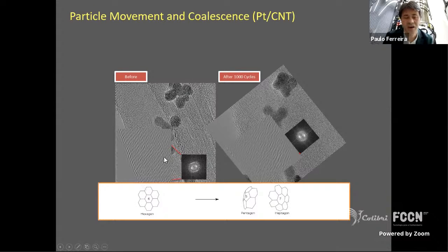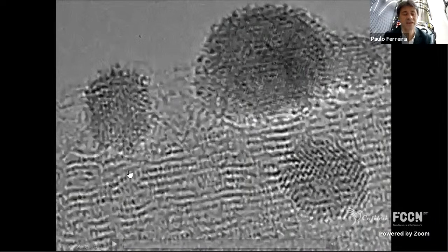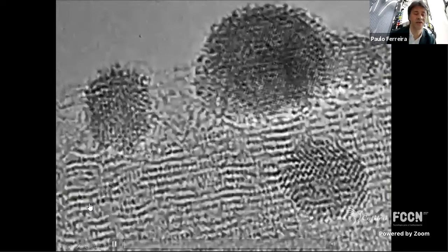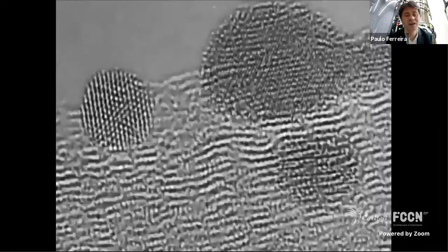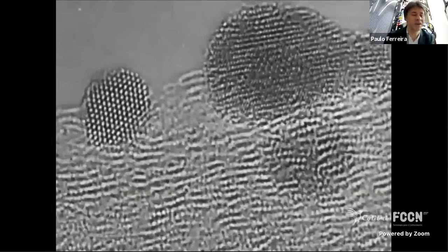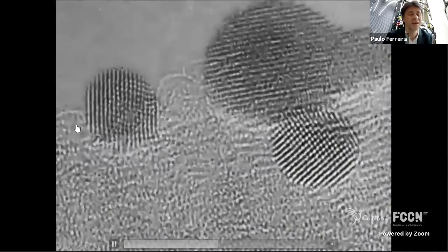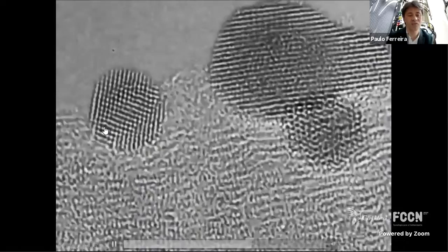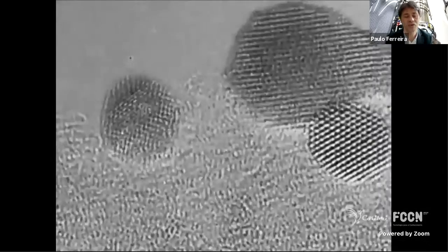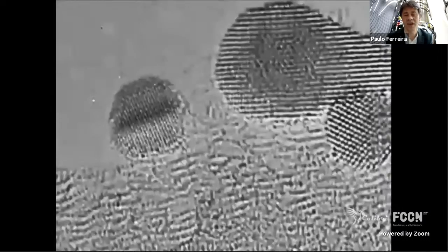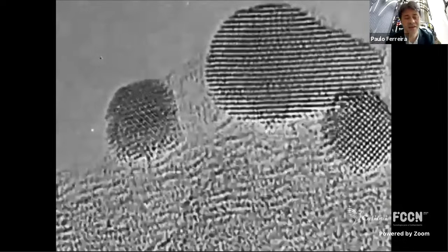This is typical of the case where you have a hexagon structure of the carbon, and when you start to get carbon vacancies, when you move from hexagons to pentagons and heptagons, you start to get this wavy structure because of the bond angle. Therefore, this is a result of carbon corrosion going on. And this allows us to look at this in real time in the microscope. So, for example, you see here very small nanoparticles, and you can see them in real time. As the carbon gets corroded, on the left of this particle, you see the particle start moving. This is the mechanism for motion: as carbon corrosion takes place, the particles start to move. So you can get a huge insight into what's going on here.